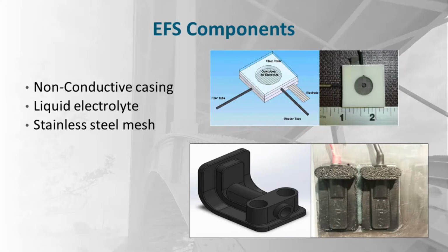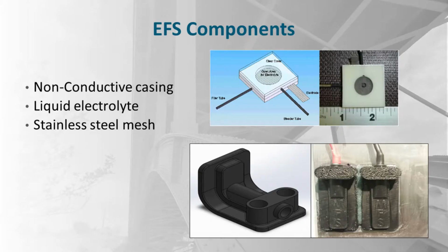So the first component is the sensor itself. It's made out of a non-conductor casing, a liquid electrolyte that is put inside of the cavity, and I think a stainless steel mesh that provides the voltage to form the passivation layer and read back the current coming from the sensor. The sensor on the top, like I said, is the short term. It's made out of foam. It's made to last up to 10 days. And you have ducts that you can use to put the electrolyte in the cavity, and that way you have the formation of the passivation layer.